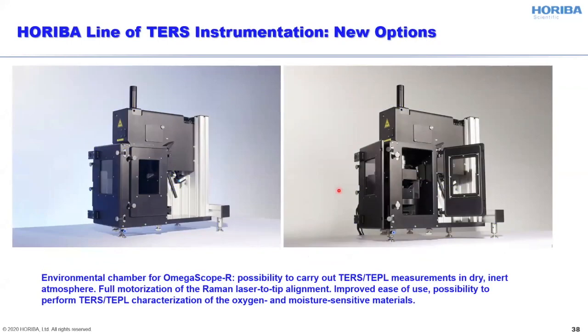Okay, so now we can switch to instrumentation again, and I will present the new addition, or new option, in our OmegaScope line of products. Now we have, starting from this year, an environmental chamber that can be attached to the OmegaScope instrument, which allows us to conduct TERS measurements or tip enhanced PL measurements or any AFM measurements under protective atmosphere. So we can purge this volume with inert gas, thus eliminating water vapors and oxygen. And this allows us to work with oxygen and moisture sensitive materials like black phosphorus, tellurides, and other important two-dimensional semiconductors, which perish very quickly in normal ambient conditions.